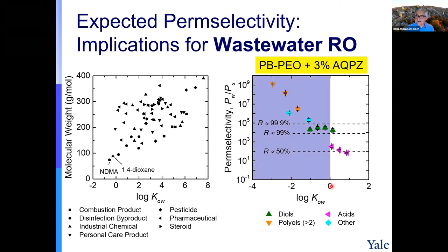And let's see here. This is the area, anything that is hydrophilic, or negative log KOW, we know that it will be rejected quite well because it's hydrophilic. And anything that is hydrophobic will not be rejected well, as you see based on this data, rejection less than 50%. And when you project it here, we have a real trouble because this area, all these organic contaminants, although they are large, they're hydrophobic.